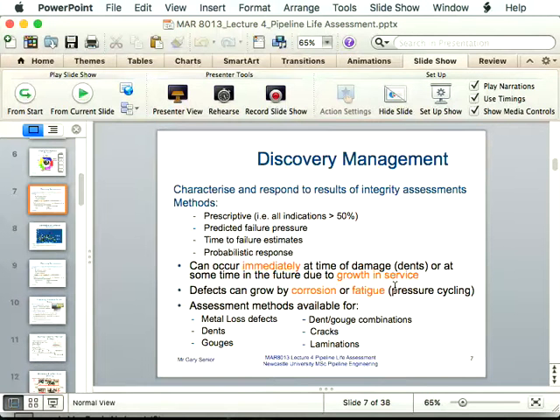So metal loss defects are the defects that you'll come across more than any others, and they generally are just simple corrosion. They use the likes of what's called B31G, which is an appendix to ASME B31, and they use an advanced technique called R-streng that I won't get into at the moment. Lots of experimental tests have been done over the years, failing corroded defects and then working back empirically, based on the theoretical data, to what the safety factors are. So lots of tests have been done failing actual and artificial metal loss features and then coming up with rules for how to assess and predict at what pressure a defect would fail. So that's for metal loss features.